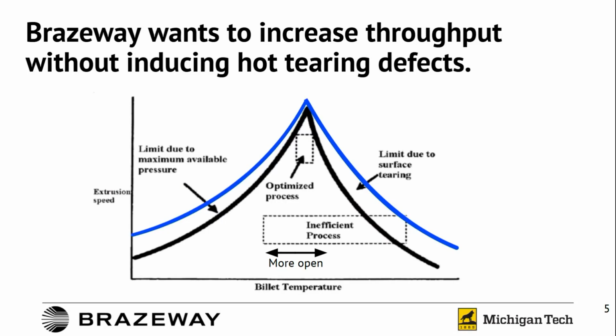One of the parts of our project was making developmental alloys off our 3102 alloy, which essentially involves expanding the process window because we want to run hotter or faster. That ends up having more friction, which can induce hot tearing if it exceeds the solidus temperature. And one of the things we're trying to focus on is creating alloys with higher solidus temperatures.